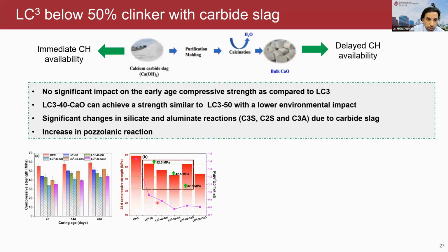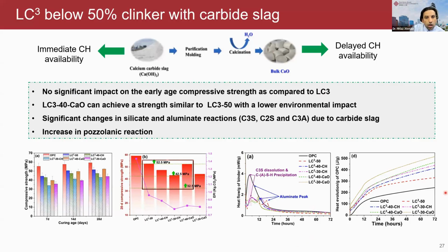And if you look at the environmental performance index, because other research used commercial calcium hydroxide, this commercial calcium hydroxide actually has a higher amount of carbon emission, even more than Portland cement. So it does not make sense to use this kind of commercial calcium hydroxide. This carbide slag, which is a waste source of calcium hydroxide, can significantly improve the environmental performance index. The lower the EPI, the better the material. And at the same time, it can maintain the same compressive strength as LC cube 50. Also, as compared to LC cube 50, it significantly improved the reaction of the system.